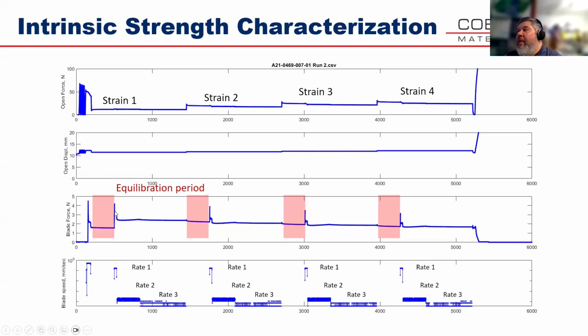Once everything's in equilibrium, then we begin to move the blade to cut the rubber. And we cut the rubber at three different rates. The first step is a very fast rate, right? So the bottom chart is the cutting rate as a function of time. You can see in the first step, we start at a high rate, that's rate 1. Then we cut the rate by a factor of 100, that's rate 2. And then we cut the rate by a factor of 10, that's rate 3. So from the highest rate to the lowest rate, it's a factor of 1,000 in cutting rate. And I'll explain why we do this in a minute.